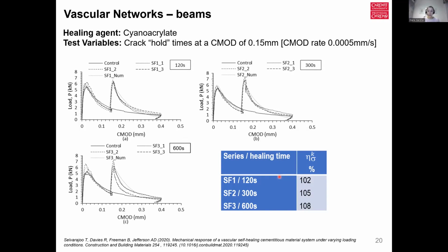So we held these cracks open for set periods of time, allowing the cyanoacrylate to cure before proceeding with the loading. The results showed a modest increase of healing index from 2 to 5 minutes, although the results suggested that healing was substantially complete, about 90% of it within the first 2 minutes. A clear trend in all of the test results is that the post-healed softening branch of the load CMOD curves, so this is second stage here, and here, and here, we had graphs which are steeper than the corresponding pre-healed response, which is consistent with the fracture energy of the healed material being lower than that for the virgin material.